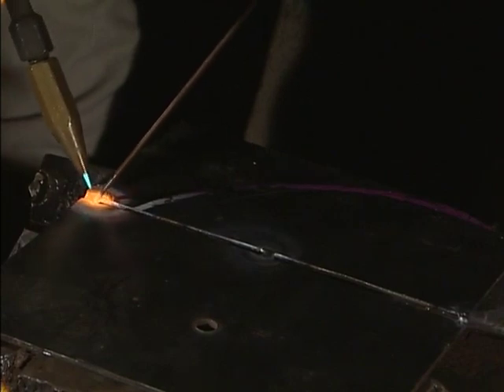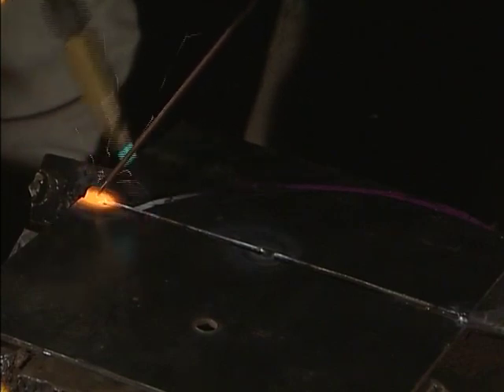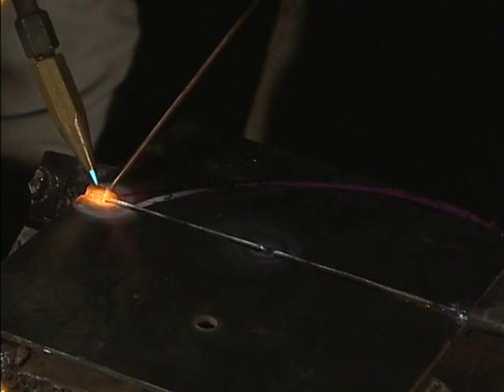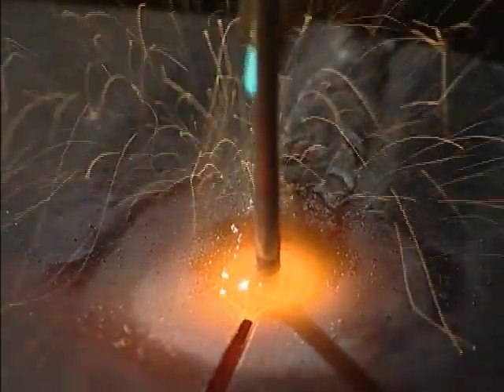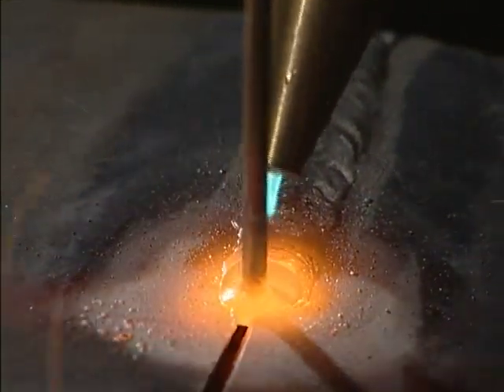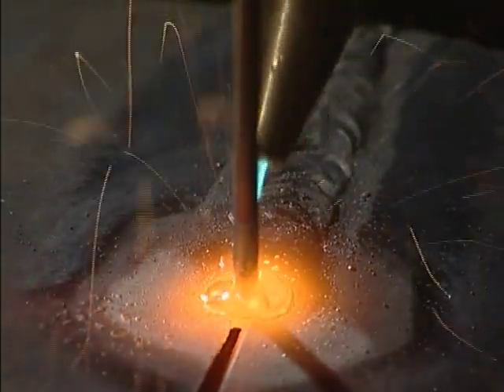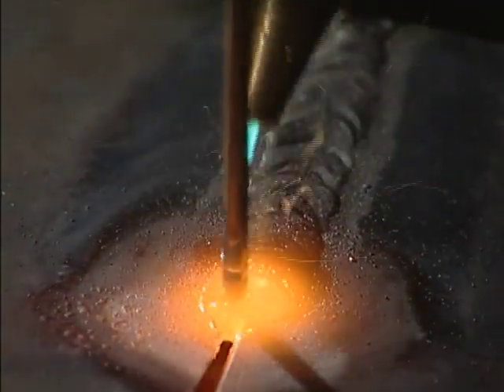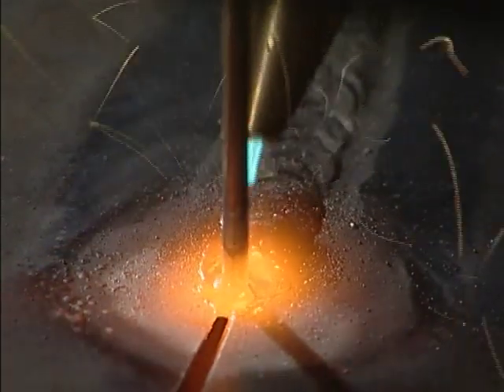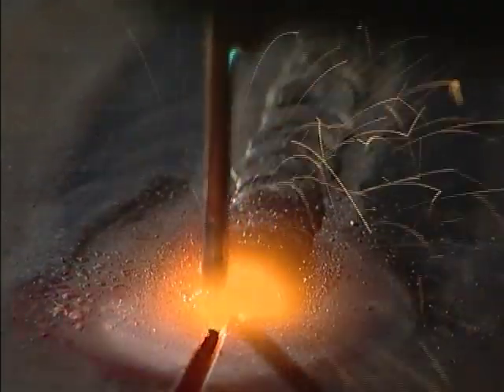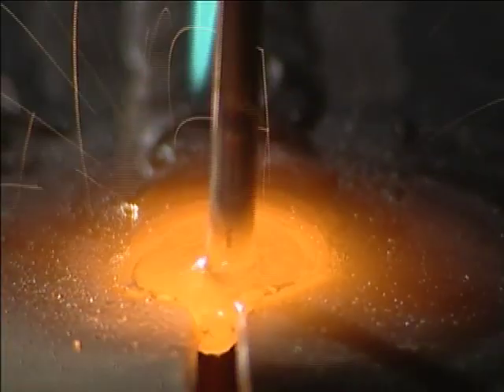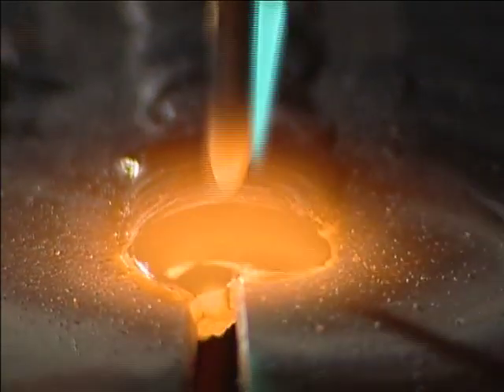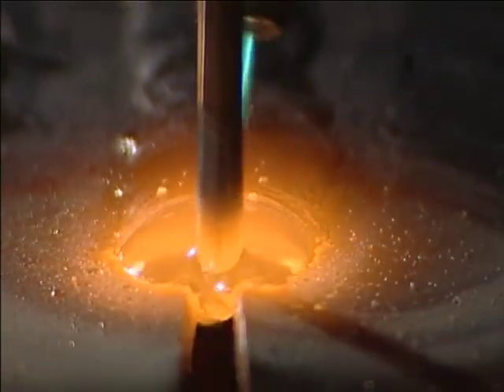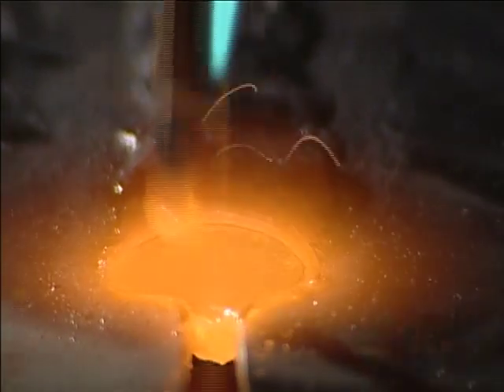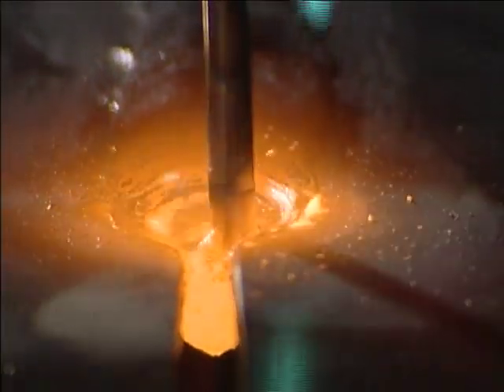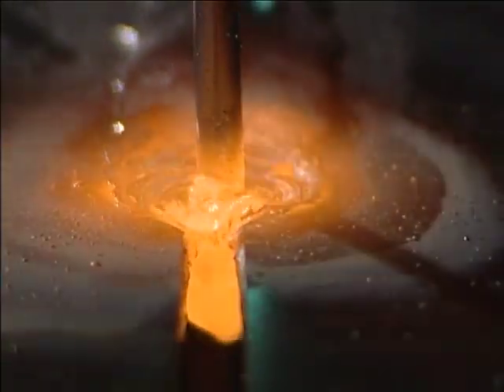Remember that the main purpose of butt welding is to securely fuse the plate's roots. Welding rod feeding serves a secondary purpose of filling the gaps between the roots to facilitate beading. Heat the 2 plates uniformly and proceed with welding at a uniform speed while paying attention to the size of the small hole made at the tip of the pool. At the end of the weld seam, feed a sufficient amount of welding rod to fill in any craters.